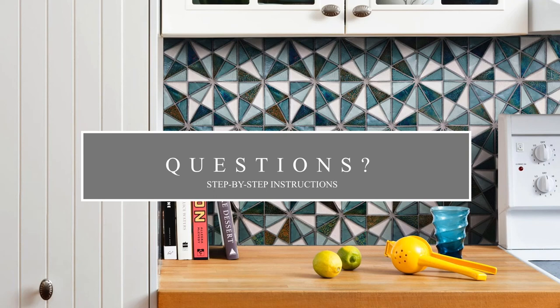If you were to remove a piece of tile after the tile fully cured, should you see thin set stuck to the back of the tile? And should it be more than a ghosting of thin set on the back of the tile? Yes, generally, if you have a properly installed tile, you should see a little bit of thin set on the back of the tile and a little bit of thin set on the substrate. So you have what's called a cohesive failure at that point. There's a little bit of thin set left. That should be the case, yes.